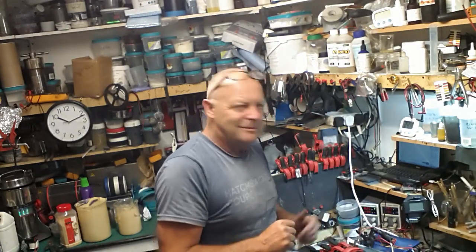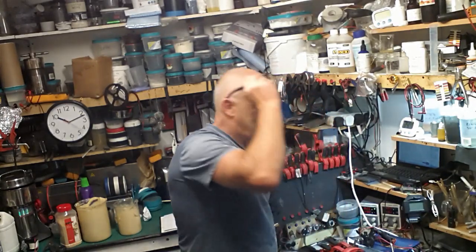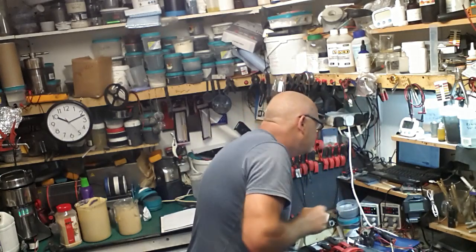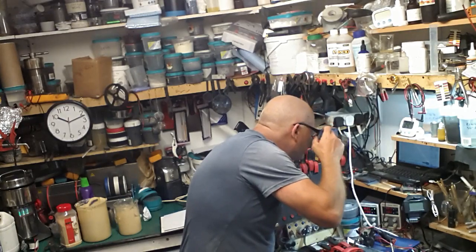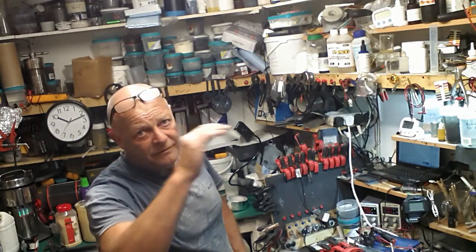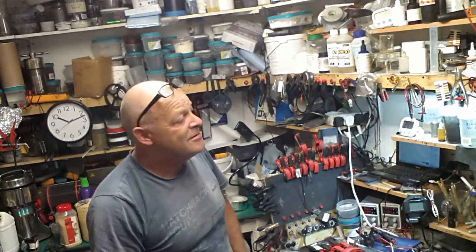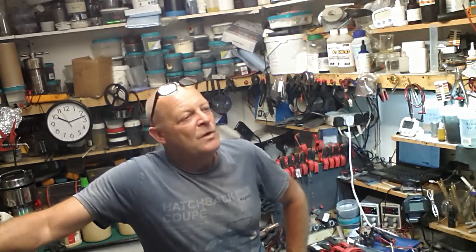So, still running. Just going to check. Yeah, 74 milliwatt hours. 2 hours and 3 minutes. 62 milliamp hours. And that's from 1 gram of material. 0.5. I haven't worked it out, and I'm not even going to try at the moment. It's quite late. I've had a long day. 10 after 10 PM. So yeah, that's this segment of the video then.